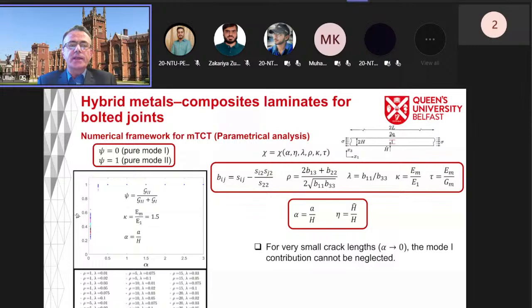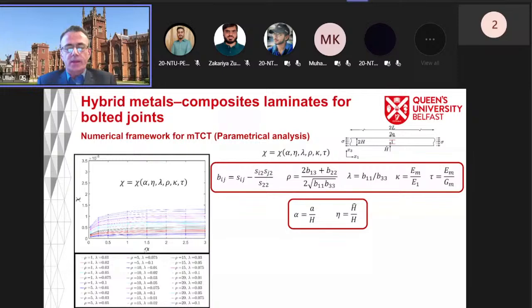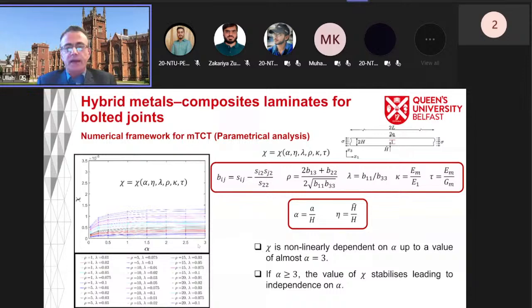In addition to this, we can also calculate this X here. So if you plot this X versus alpha for different materials, you can clearly see that X is non-linearly dependent on alpha up to a value of almost 3 here. And then if alpha is greater than or equal to 3, the value of X stabilizes, leading to independence of alpha. Now, obviously, we want to satisfy both conditions of mode mixity and this X. Therefore we are choosing a value of alpha, which is 3 in this case.